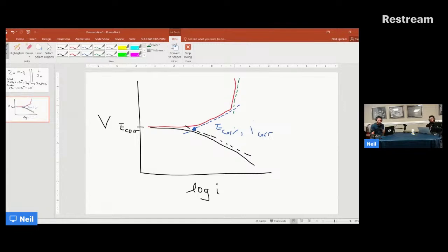But you start to get that formation on the surface, which is why this starts to go more vertical often, because you can just look at the axes. For example, the voltage is getting higher, but the current is staying roughly the same. I mean, it's log of current, but basically as you increase the voltage further and further, you're not getting more current out of it, which is sort of antithetical. You'd think that as you increase the overpotential, you would get much more current out of it, but you reach a limit where you're just not anymore.